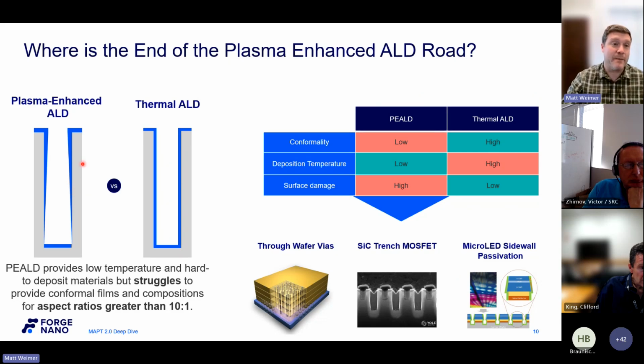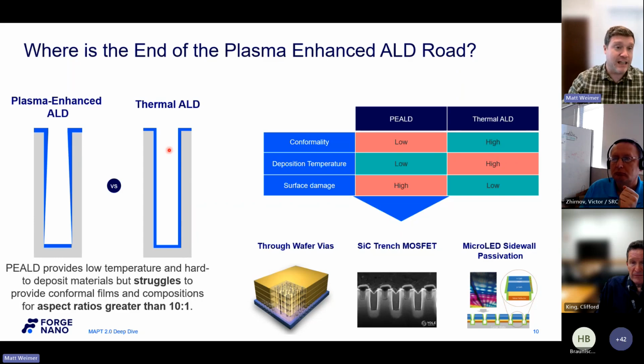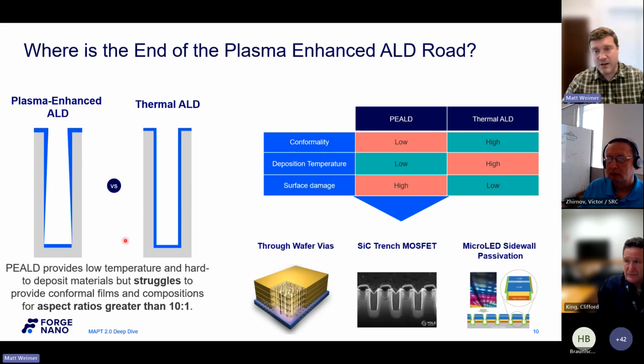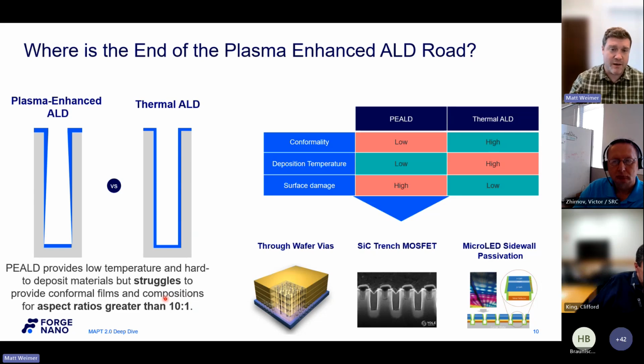In my experience, what typically happens is at some point, your composition will start to degrade before your thickness will. And that's simply because you don't get enough radicals or ions on the surface to densify the film, right? So those species are what are required to do the conversion. With thermal ALD, it's not limited in that same respect. So there's a lot of examples, especially with metal films, where once you get to about 10-to-1, the aspect ratio starts to really struggle. Now with oxides, oxygen radicals live a lot longer so that you get a lot more runway. But I'm setting up that later, we'll talk about metal films. And so here's some examples of where we think this will really play in.